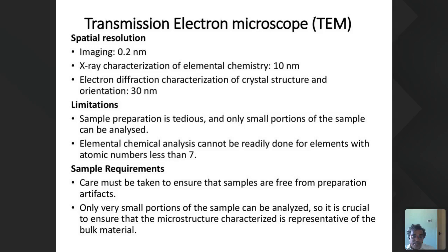Care must be taken to ensure that samples are free from preparation artifacts. That means when you are making the preparation, nothing from the preparation should be left on the sample. Only very small portions of the sample can be analyzed, so it is crucial to ensure that the microstructure characterized is representative of the bulk material. That means the bulk material from which you are going to create the specimen should have a uniform character. Then only can you take any sample out of the bulk material, and it will correlate better.